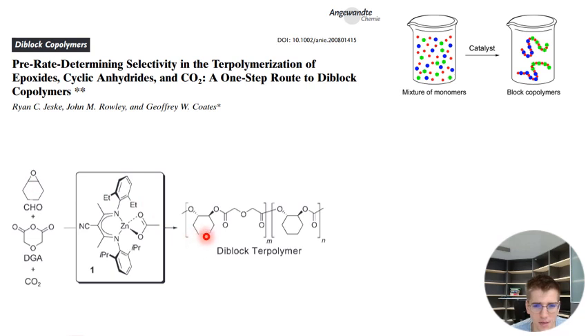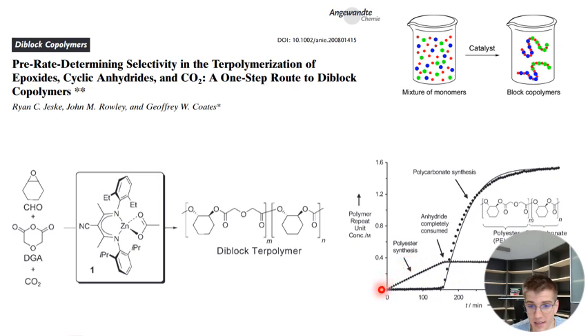Yeah. But what they found is when you mix all these three monomers with this zinc catalyst, you form a block polymer. So what happens first is that polyester forms from the DGA here and the CHO, this is supplied in excess. And then once all the cyclic anhydride is consumed, the copolymerization of the CO2 with the epoxide occurs. That really only starts once this is consumed. Yeah, it has to do with the fact that the alkoxide intermediate that originates from ring opening the epoxide here inserts orders of magnitude faster into the anhydride here than into CO2. And in that way, you got this block polymer selectively from a mixture.